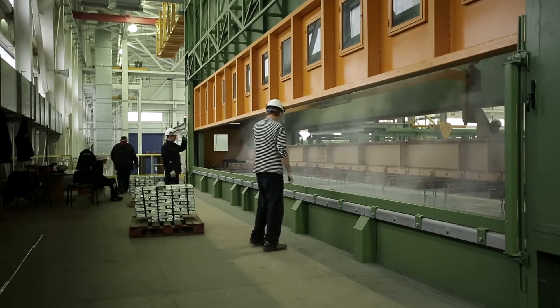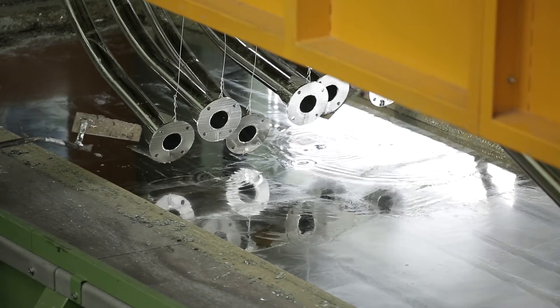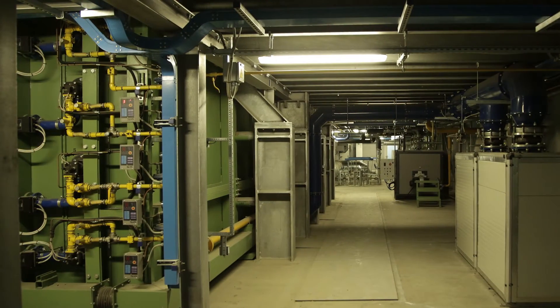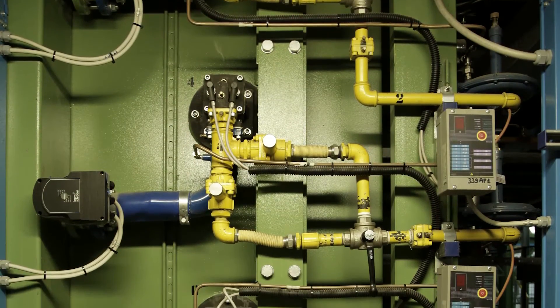The furnace plays a role too. Here we have the latest generation of dual chamber furnace, a concept strongly based on controlling heat input in the upper and lower chambers to allow a temperature gradient of up to 7 degrees Celsius in the molten zinc bath.